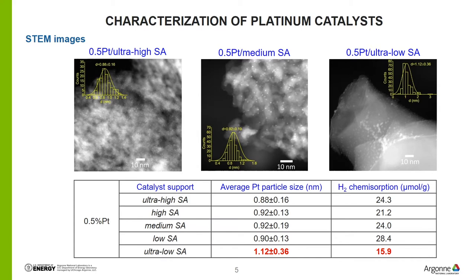So the goal of this project is to stabilize the size of those nanoparticles. The only exception is for the catalyst on the ultra-low surface area support — the particle size is 1.12 nanometers with a wide distribution. Also, the chemisorbed hydrogen amount on this catalyst is 15.9, which is the lowest value among those catalysts, again showing larger Pt particles formed. The hydrogen chemisorption experiment uses hydrogen to chemisorb on the surface Pt atoms; the larger the particle size, the less hydrogen chemisorbed for the same Pt weight percent. This ultra-low surface area catalyst is good for ALD but not for catalysis, so ALD overcoating will not be applied on this catalyst.